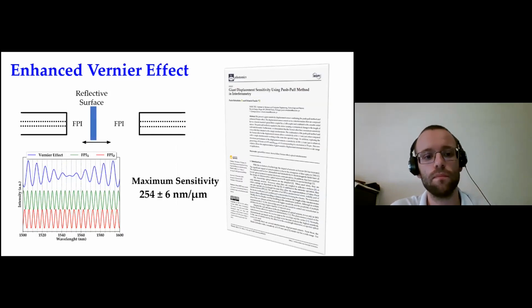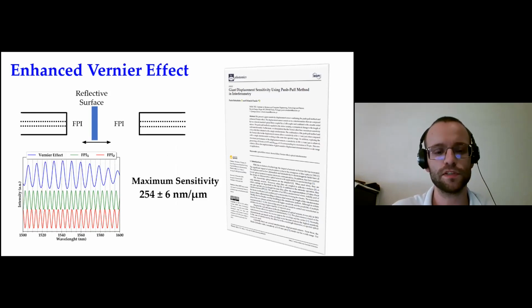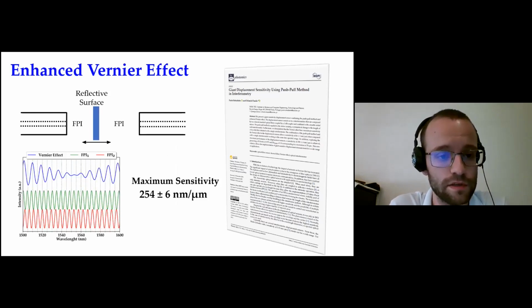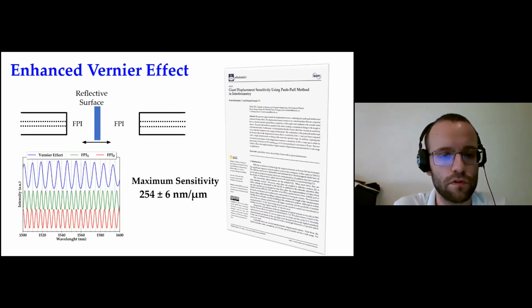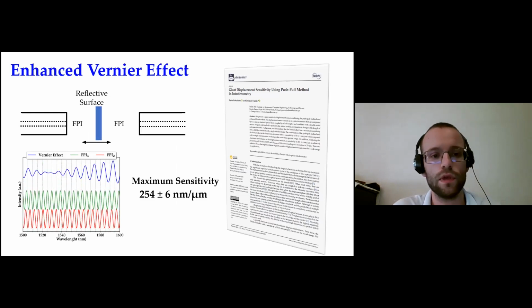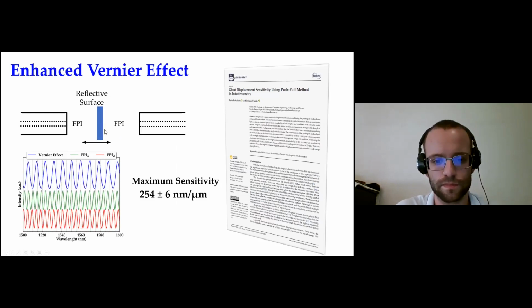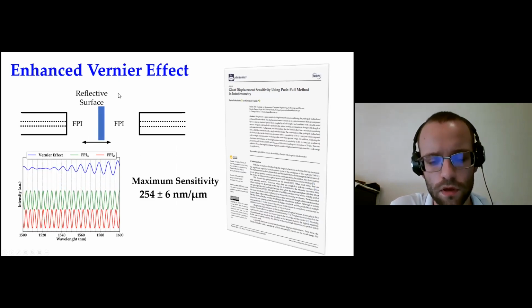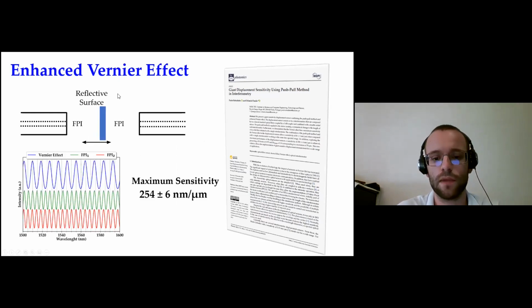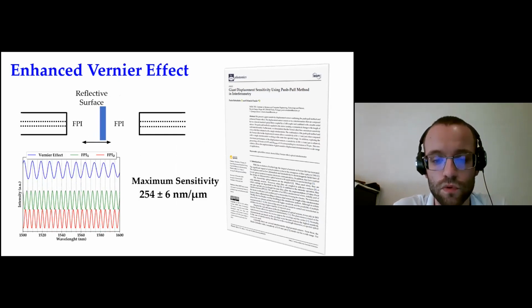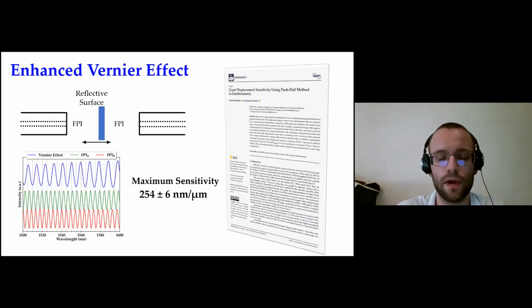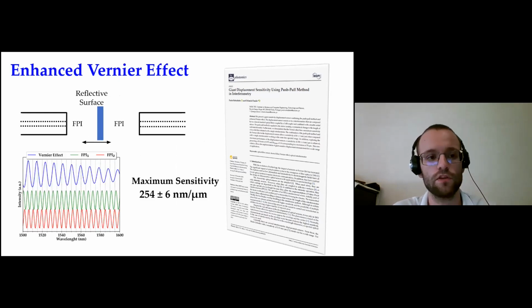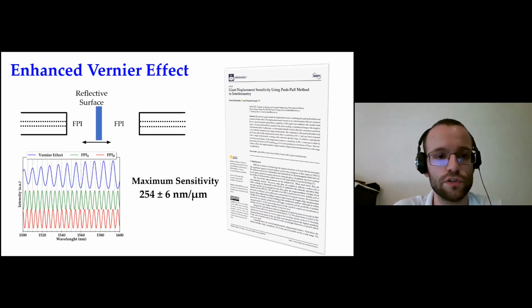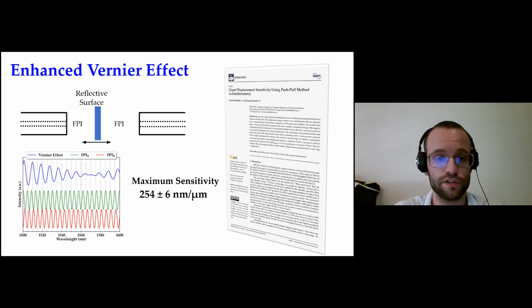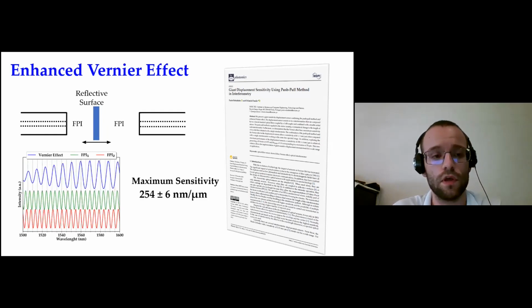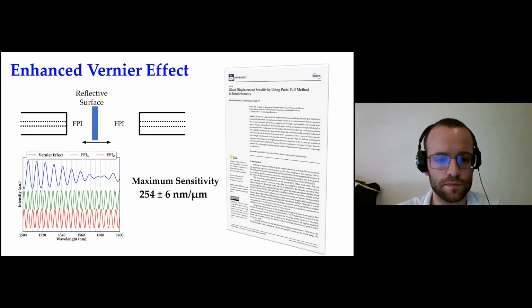After this, we implement this concept in a displacement optical fiber sensor. We use two Fabry-Perot interferometers, and in the middle we have a reflective surface. With this setup, we obtain a maximum sensitivity of 254 nanometer per micrometer, which is much higher when compared with other sensors that use the traditional Vernier effect.